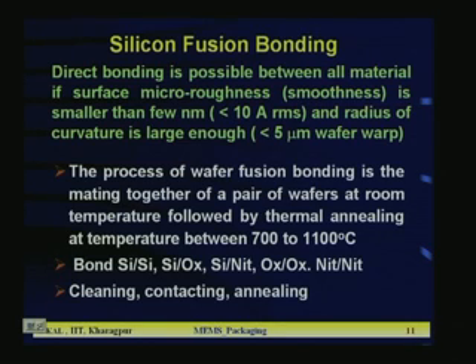The process of wafer fusion bonding is basically mating together of a pair of wafers. Two wafers are brought into contact, and before contact you have to clean them thoroughly, and you make contact of the two wafers at room temperature, and then the combined pieces are treated at high temperature for annealing. Thermal annealing is done at a temperature between 700 to 1100 degrees C, and in this case of fusion bonding you can get silicon silicon bonding, silicon oxide bonding, silicon nitride bonding, oxide oxide bonding, and nitride nitride bonding. So, all kinds of bondings are possible in fusion bonding.